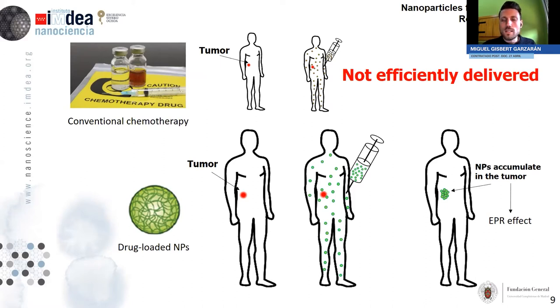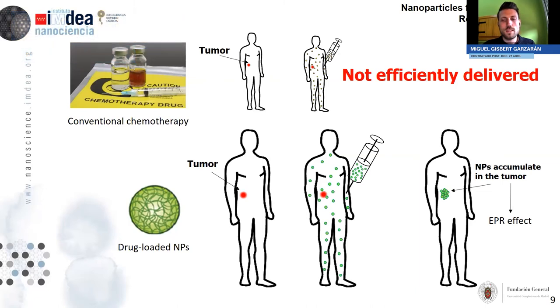Why are those nanoparticles going to accumulate in the tumor? Well, there is something called the EPR effect, which stands for enhanced permeability and retention effect. And this is a very characteristic feature of tumors that consists of the fact that tumor tissues are defective and they present very poor lymphatic drainage. And also the blood vessels around the tumor are leaky, meaning that they have small holes. So in the end, the combination of those two facts allows nanoparticles to leave the bloodstream and accumulate in the tumor because of those holes. And then because the lymphatic drainage is very poor, the nanoparticles will remain for long periods of time in the tumor.